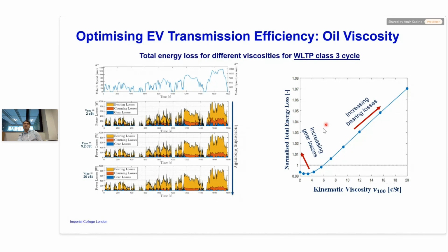What we've got on the right-hand side is a total loss. We've normalized it here, not to show the real numbers, and we've got kinematic viscosity here. What you can see here is, depending on your oil viscosity, the loss will change. You're not surprised, right? The interesting thing is there's an optimum. For the WLTP and that particular unit, it's around 3 centistokes.